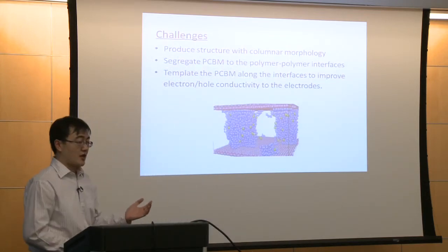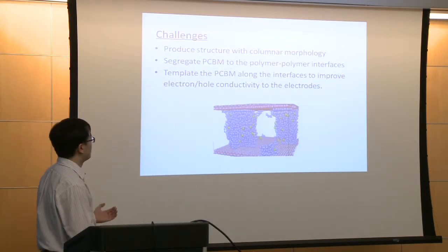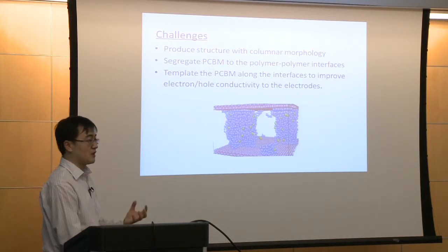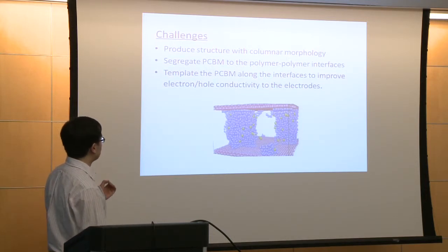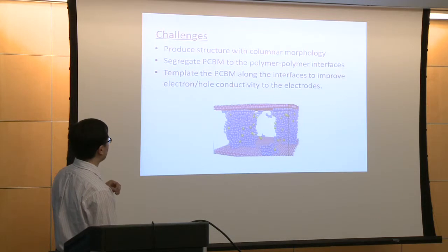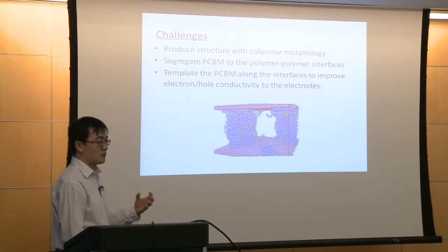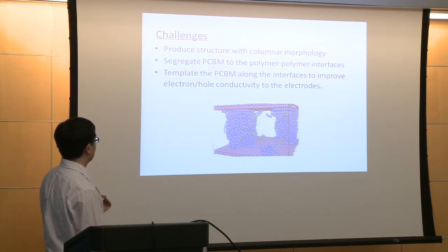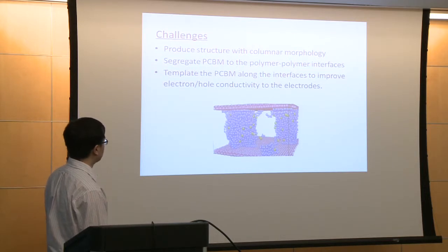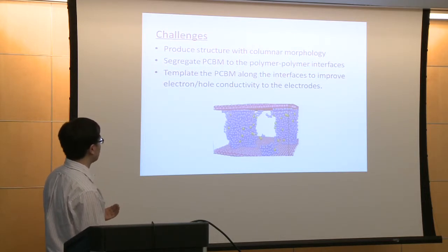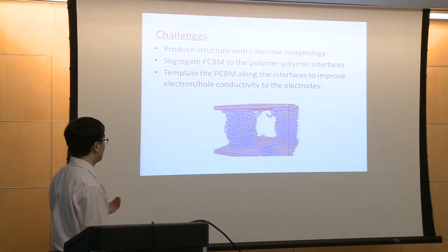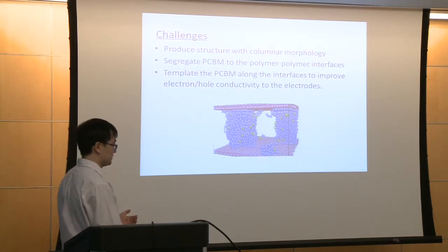So these are the challenges we are facing too. First, we need to produce structure with columnar morphology. And second, we need to try to segregate the PCBM to the polymer-polymer interface. And third, we need to template the PCBM along the interface, as I said, to improve the hole conductivity to the electrodes.